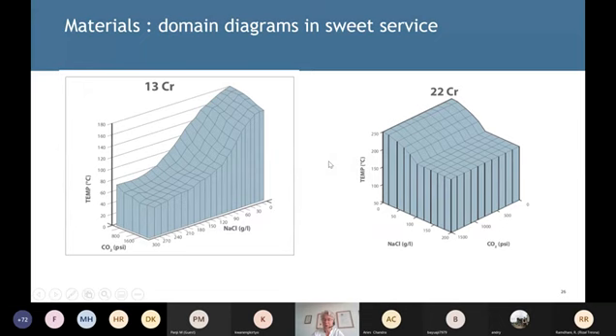Now, these diagrams I'm quoting here are from a Nickel Institute publication I produced with Dr. Bruce Craig, and it was updated in 2011, and basically these are saying that if the temperature exceeds the upper surface of these 3D contour diagrams, then you'll start to get a breakdown in passivity. So we rely upon the chrome oxide film on the surface, but that film is affected at certain temperature conditions. What we also know is that there is a pH at which the passivity is broken down, and with some oil conditions we can definitely get below the passivity stability pH, and that can cause pitting.